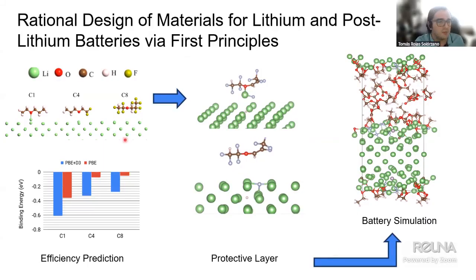We start with predictions or calculations that are very simple. In this case, we have 3 compounds and we put them over a surface of lithium and we see how they react, or which one reacts with a higher energy or with a higher interaction. Then that can help us predict some of the reactions that happen between those components or solvents and the surface of the anode or the cathode. And that can help us predict what is going to form at the SEI layer in the battery.